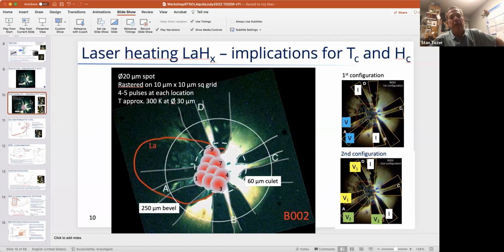We did not do that. We had pretty tight spots. Well, we had 20 microns. Sorry, his was larger. I think it was 60. But then we rastered across in a very discrete square pattern. So we came across here, we hit it about 4 to 5 times, and then moved over, hit it 4 to 5 times, and continued across the sample that was of interest between the electrodes.